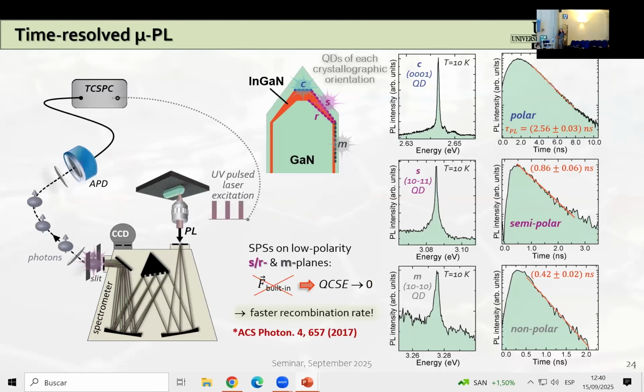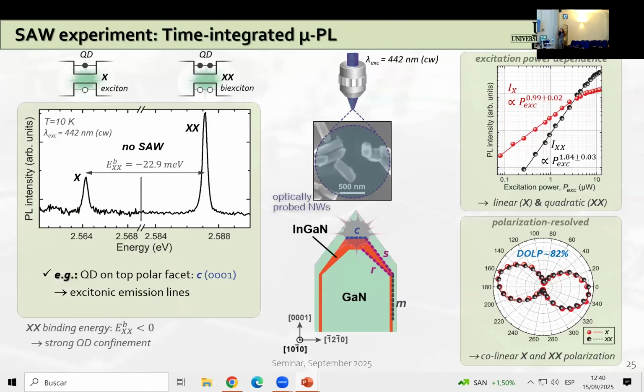We also performed time-resolved micro-PL experiments, and as expected, we observed that semi-polar and non-polar quantum dots indeed exhibit much faster recombination rate compared to the polar ones. And this is, of course, because the built-in electric field and therefore the quantum confined Stark effect is basically absent on these low polarity planes, as we expected.